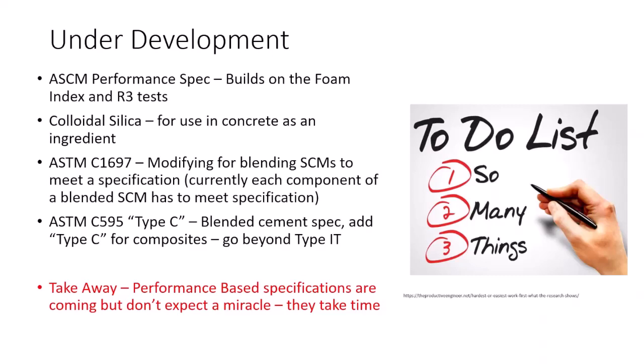We're working to modify existing standard C1697, for blended SCM. So you could take a fly ash and a slag or a different pozzolan, 2 different materials, put them together and meet it. But right now it says each one of those individual materials in your blend has to meet a standard on its own. So if you had a fly ash that didn't meet one requirement, say the fineness or loss on ignition, you couldn't use it in that standard as a blend. We're trying to change that, open it up so the final product meets the spec, not the individual ingredients. And that will open it up to more accessible use of a number of materials.